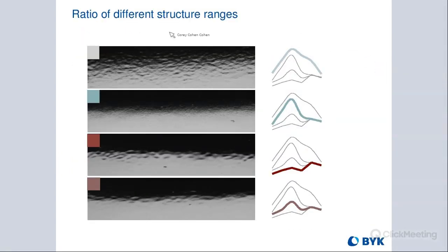So this is just those same pictures shown again in its various stages. We took this very, very wavy surface and optimized the clear coat to bring down those longer structures, and that gave it a sandy look. And then we brought down the shortwave structures by sanding the primer to make the primer smoother before putting on the top coat.